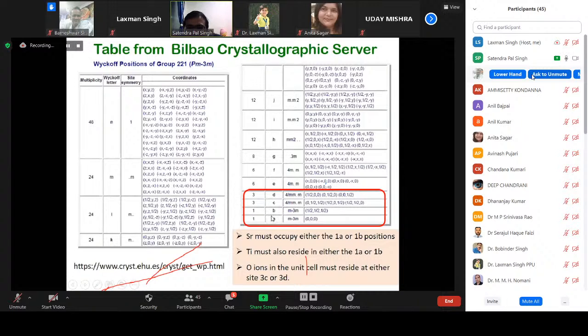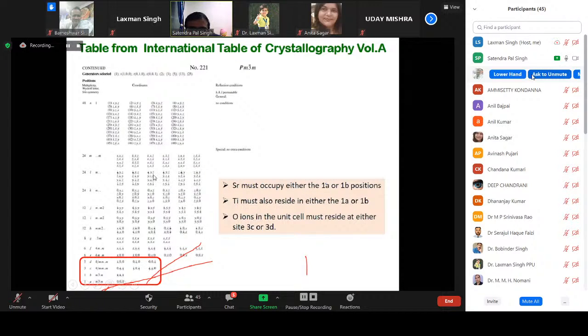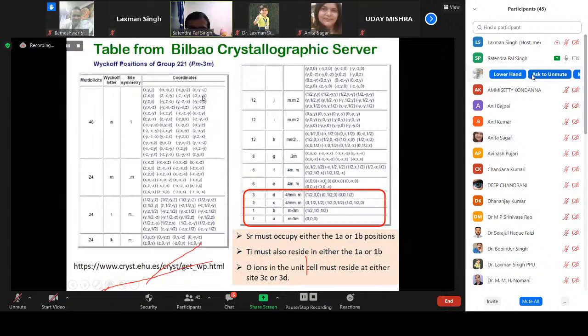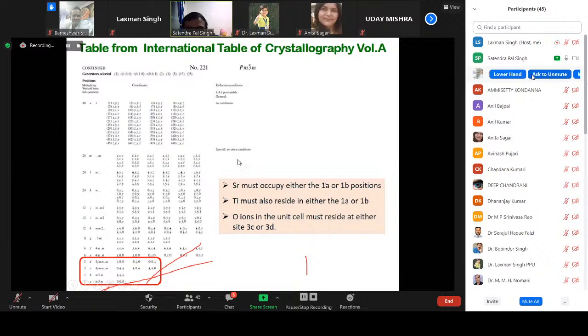Then a little bit of confusion. What do we have to do? Let us put strontium at the 1a site and titanium at the 1b site. Which site will the oxygens be, D site or C site? That we'll find out. This is a table from the Bilbao Crystallographic Server, and you will get this kind of pattern from the International Table of Crystallography Volume A. You should have this, and it is freely available. You can just check from the internet. And if you have the crystallography table, which is a big volume of books, you can generate these things.